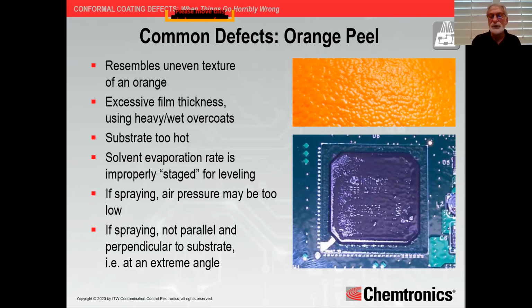And what happens is that as soon as it hits that warm substrate, there's such a delta there that solvent starts flashing, and it's flashing unevenly. And this is going on as you're depositing additional coating on top of that. And so with solvents starting to flash in kind of a random manner, they form these bulges, and they form that really uneven, rough, peak and valley type texture.